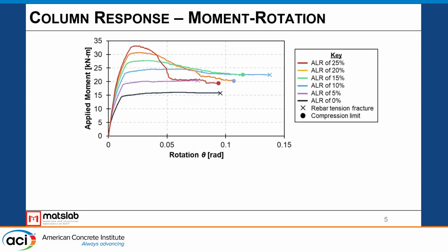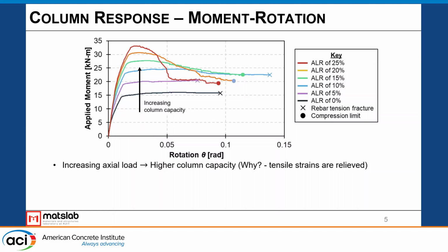From our finite element simulations, we obtained our column response. What we're looking at here is, on the y-axis, the applied moment to the column, and on the x-axis, the rotation of that column. At the bottom, we have essentially a column subjected to no axial load, and at the far top in red, we have a column subjected to 25% axial load. What we can immediately see from these responses is that as we increase the axial load on the column, we get increasing column capacity. The reason we see that is, as we apply the axial load, we're relieving those tensile strains on the tension reinforcement, and ultimately that allows for the column to yield at a higher load.